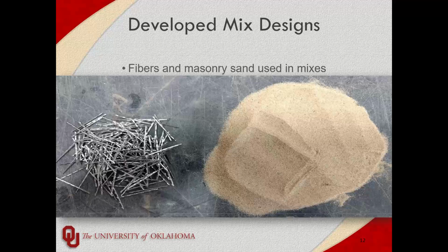So I bring this slide up mainly because in our mix design, some of the materials we use are slightly different. On the left, you see the fibers that we used, and you'll notice the most common fibers that are used inside of UHPC are kind of hair-like. They're Dramix fibers from Bekaert. They're 1/2 inch long, 0.2 millimeter diameter, little hairs. I call them little hypodermic needles when you get them in UHPC. But because of the expense, and we were trying to really reduce the cost of our mix, we decided to go with a cheaper fiber, and we ended up using these.